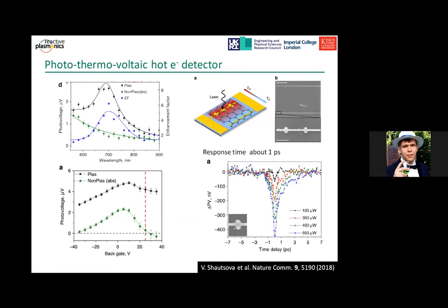us the local field enhancement, and is also expected to generate the hot carrier population, which will be driving our photothermal voltaic effect. In fact, the photothermal voltaic effect in graphene-metal junctions has already been studied before in different detectors, but usually it's driven by the difference in Seebeck coefficients between graphene with a metal overlay and surrounding graphene. So it's only observed at the contact areas. That's exactly what we see when our non-plasmonic contact is illuminated with light.